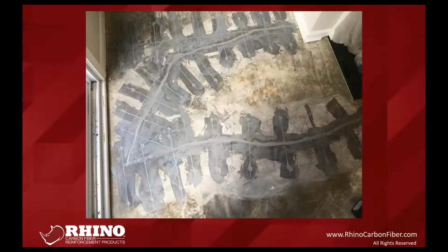This is another example, very similar situation. You can see here there's actually a control joint that was cut. It started to do what it was supposed to do, but then ultimately failed to break and then split off over here towards this sliding glass door and then re-cracked back here as well. So not only did they fix the crack, but they also locked this joint down to keep it from re-cracking in the future.